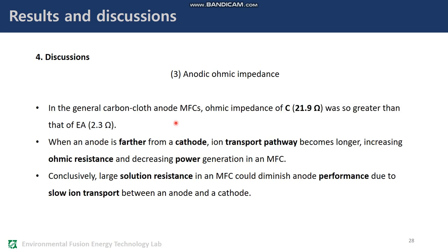In the carbon cloth anode MFCs, ohmic impedance of C with 21.9 ohms was so much greater than that of EA, 2.3 ohms. When an anode is farther from a cathode, ion transport pathway becomes longer, increasing ohmic resistance and decreasing power generation in an MFC. Conclusively, large solution resistance in an MFC could diminish anode performance due to slow ion transport between an anode and a cathode.